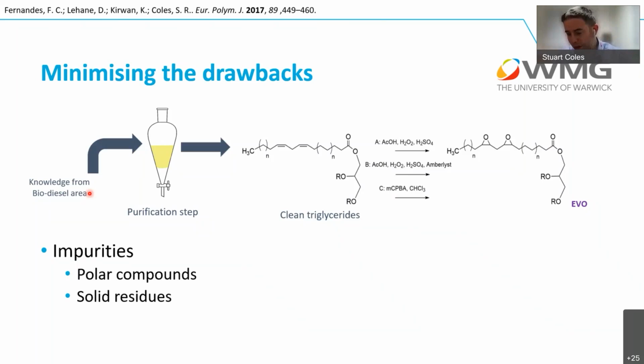Maybe some of even the monoglyceride, some of the more water soluble materials, they all come out in that purification step. And what you're left with is a vaguely clean triglyceride material. Not perfectly clean, but it is certainly a lot cleaner than it was before doing that step. From there, we knew that there was still some double bonds in those materials, so that gave us the door opening to allow us to get in there and do some functionalization with these materials. We tried a number of different routes with acetic acid and a little bit of sulfuric acid. We also tried a more traditional organic chemistry route using MCPBA and chloroform.